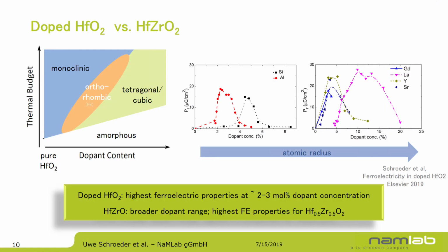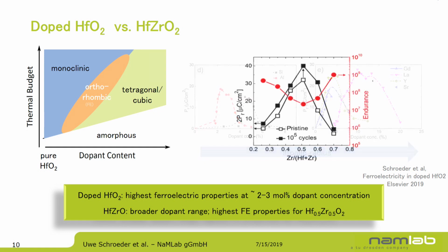Okay, and this was shown for all different kinds of dopants here, from silicon to aluminum, which are smaller than hafnium, to dopants which are larger than hafnium. You can always see there was a certain range where you get the ferroelectric properties of the material, and with increasing atomic radius of the dopant, you could also see that the process window was increased for the larger dopants, for example, like the lanthanum case. And the system most people are currently looking into is the hafnium zirconium system. Again, you would have in between the monoclinic hafnium oxide and the zirconium oxide a region where you see the ferroelectric properties of the hafnium zirconium oxide, and this is about 50% hafnium and zirconium, where you see the highest remnant polarization value.